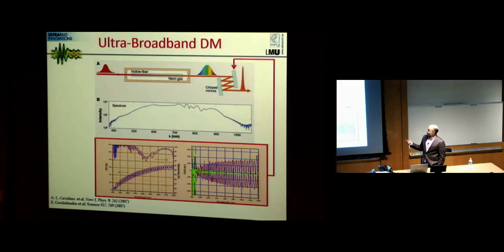One of the ways to generate a short pulse is that you need to generate a broad spectrum, and one of the easiest ways to do it is to use a hollow core fiber where you send a relatively short pulse of 10 to 20 femtoseconds. Then due to the nonlinear effect, you get a broad spectrum as shown in this figure. And then you need to compress this stretched pulse. One of the ways to do it is to use broadband chirped mirrors. And for example, here is one example of these mirrors.